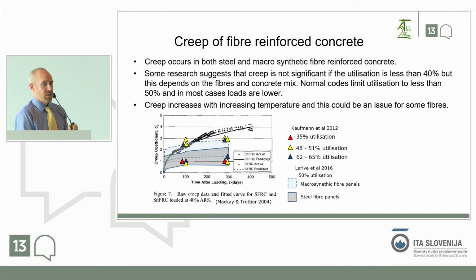Creep's quite a complex process. It takes quite a while to digest the data. But my overall conclusion from that is that yes, macrosynthetic fibers creep more than steel fibers, but not so much more in the conditions we're talking about that it's a problem. If you have a different situation, if you're working, for example, in the Middle East, you've got an ambient temperature of 30 degrees, your creep is temperature dependent, of course, you've got some extreme loading, then it's something perhaps to worry about, but not in most cases that we're looking at.